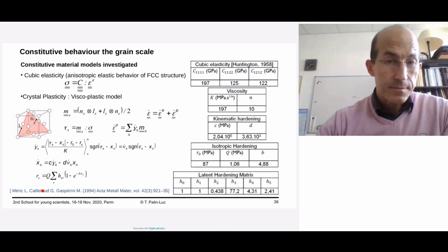So in fact, the cyclic hardening and the cyclic softening of the material are written by equations for each slip system, defined by the normal to the plane, the vector n subscript s, and the vector l subscript s, fixing the direction of sliding. So one example is the model proposed by Méric and Cailletaud at the end of the last century, but you can find other models also proposed in the literature, and there are very famous simulations done in the literature by Fionn Dunne and colleagues in the UK.